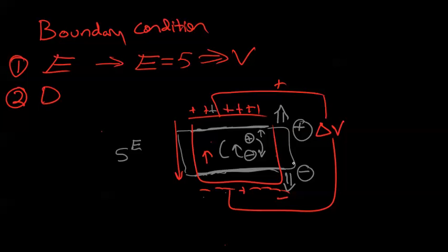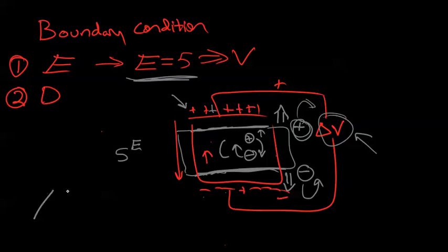But this is a charge imbalance, and we are forcing the material to undergo a certain electric field. Electric field is directly related to how many charges are on the surface. So when you are generating more charges, the voltage source is going to absorb those extra charges and maintain the electric field at the voltage specified. So even though we pull on it, while we have an applied electric field, the electric field is still constant because of the power source.